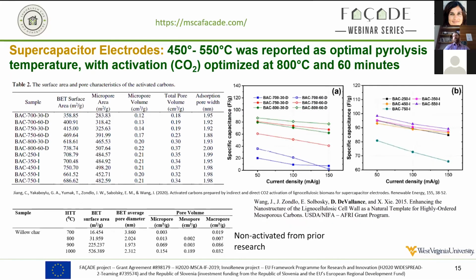Following on this research was another project that was looking at a more stepwise kind of carbonization using the same willow material as one of the species, and then seeing if you can improve the capacitance. So these are the results I'm showing in table 2, and in the graphs next to it are this willow that went through a pyrolysis route of different steps. It was carbonized to 450 to 550, then stopped, and later activated with CO2 up to 800 degrees Celsius and held there for 60 minutes. So this can help tell you what this activation will actually do in terms of improving your capacitance properties.